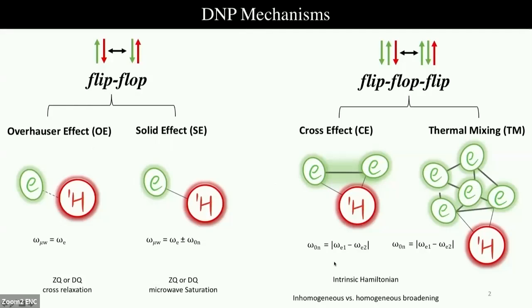The good thing about this kind of mechanism is that it's intrinsic to the system, so the interaction that is required is already present. Triple flip mechanism can be broadly classified as cross effect and thermal mixing DNP. They are very similar. The difference comes in terms of the broadening of the EPR line width. If the EPR is more inhomogeneously broadened, then it's cross effect. Otherwise, it is defined as thermal mixing DNP.